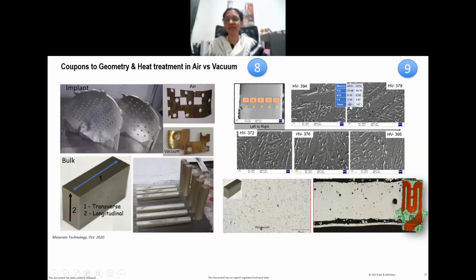So what I'm showing you on the right-hand side is genuinely a challenge in terms of how do we extrapolate not just mechanical properties, but microstructure from a bulk specimen? We normally print 1/2 inch by 1 inch, at least 3-4 millimeter thick specimens, isn't it? How do I go from there to a very thin section thickness of about 600 microns out here? How do we accommodate the heat treatment, especially in exotic materials like titanium alloys?